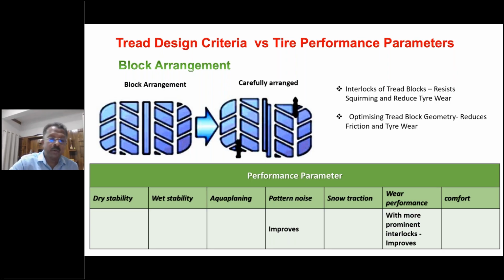And geometry of tread block. Most important, the geometry of tread block. See, geometry of tread blocks should be in such a way that when the load is coming, the tire is compressing on the footprint. See, rubber is not compressible, but rubber compresses. It expands to the different areas. So we have designed the tread block geometry, the shape, in such a way that when the tread is compressed to the footprint, there shall be minimum movement of tread element on the road side. The shape should be such that the element movement shall be off the road surface. It will reduce slip and friction.